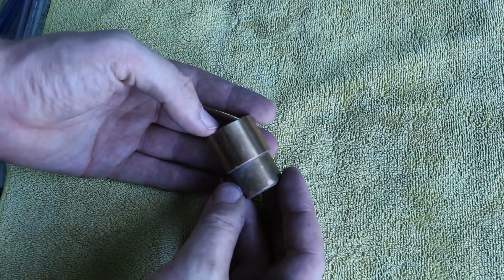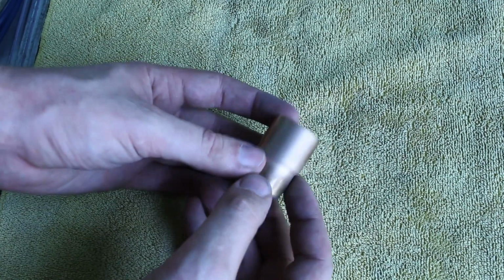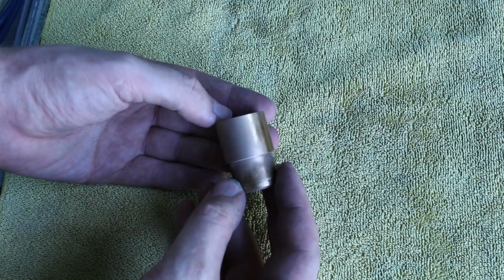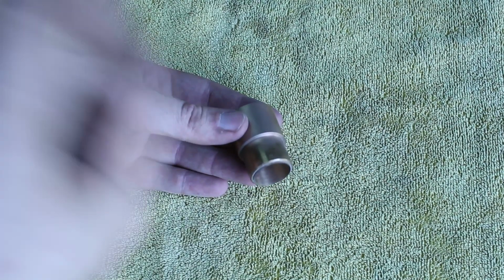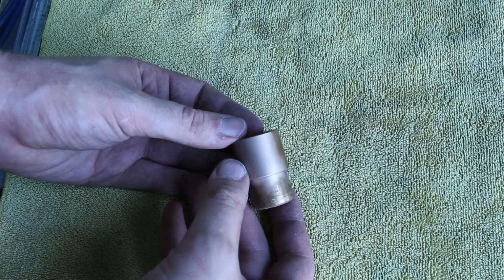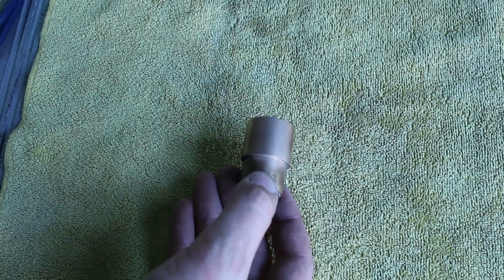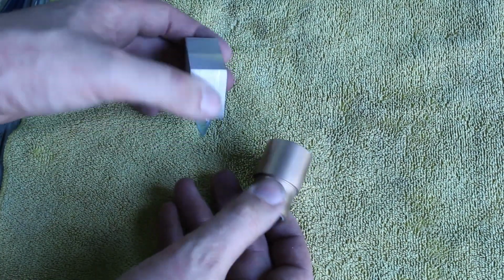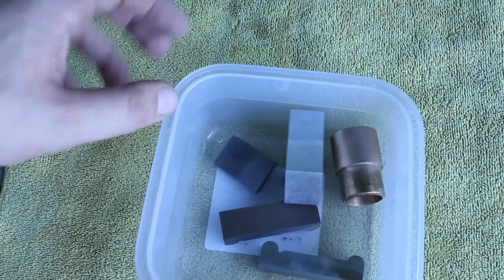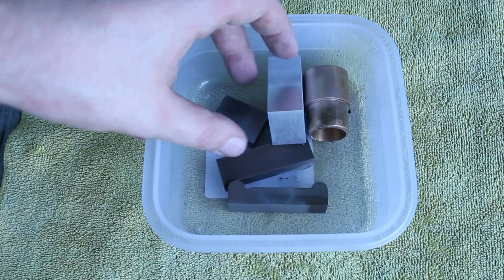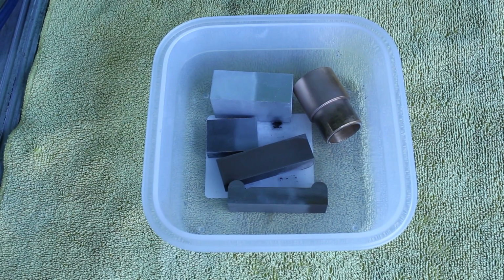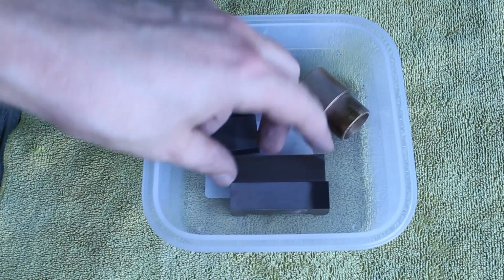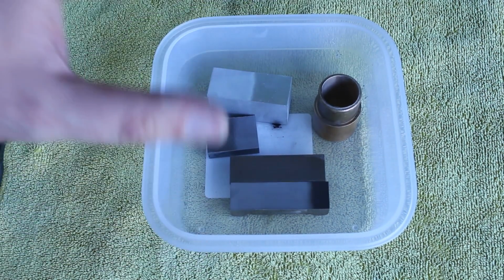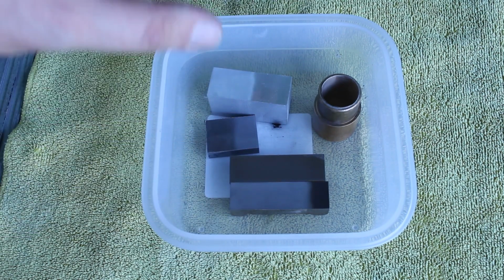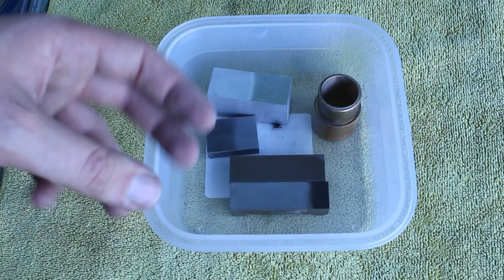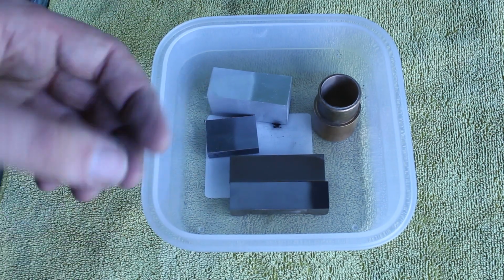And this is a phosphorus bronze bushing. As you can see, this also gets a very nice finish. You have to be a bit careful in softer materials if you run it at very high pressure. You can embed abrasive into the materials you're blasting, especially with aluminium or possibly with bronze. So that's the results I get with this blasting cabinet. I'm very happy with that. And you will probably see a lot of blast finished parts in future. Also, this works very nicely to deburr plastic parts. If you load ground up walnut shells into it, it's great for deburring plastic and giving a very even finish.